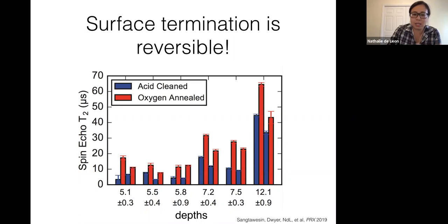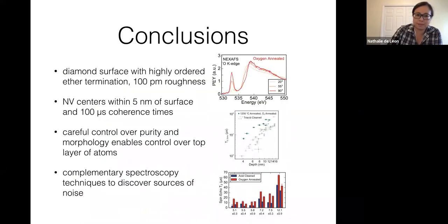And we basically see that this is true for every NV center that we look at in the sample. So we're really just monkeying around with this last layer of atoms at the surface. This would only be possible if you have very good control over the surface contamination.